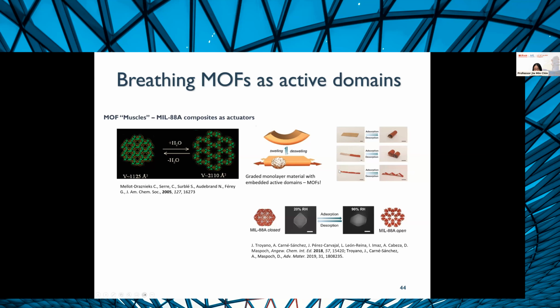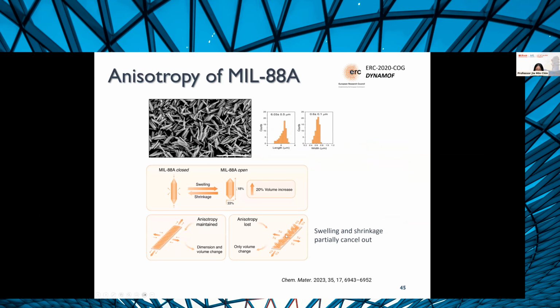And then you can end up with this kind of actuation, with absorption and desorption, and you end up with curling and straightening. However, if you look closely at how MIL-88A expands, if you go from 20% to 90% relative humidity, it expands 33% in this direction. But along the c-axis, it actually contracts about 18%. So what this means is that if you have these particles randomly oriented inside a polymer composite, the swelling and shrinkage start to cancel each other out. But if you have them beautifully packed and aligned, theoretically, you would be able to harness this crystal-based anisotropy and translate that to the macroscopic length scale.